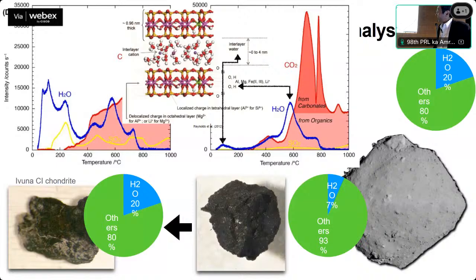So this is the real shape and real color of CI chondrite, the Ivuna meteorite, which fell 60 years ago. This meteorite was carefully stored in the Natural History Museum in London. But the sample is contaminated by exhaust gas in London. So it is atmospheric contamination. Atmospheric contamination changes the materials severely. Water content increases and the color changes. The reason for the color change is that most of the sulfur is oxidized to sulfate.